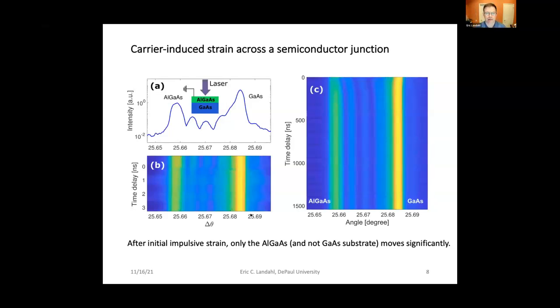This is what the data looks like. Again, there's the transparent film on top. The transparent buffer on top is not shown. This is the film absorbing at 400 nanometers, and then the very thick bulk. And the high resolution diffraction techniques allow us to record on a logarithmic intensity scale, which is enough to completely solve the structure of the material. Its strain is a function of depth because of its high dynamic range. You can see interference fringes from the layers and the peak from the substrate as well as from the film.